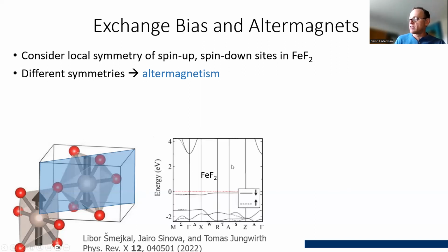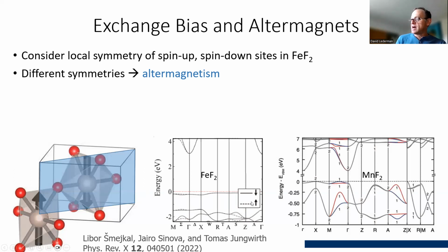And in fact, people have calculated the band structure. I think Sinova and others have calculated the band structure, taking this into account. And you can see that along certain directions in the crystal structure, right? This is like spin up and spin down, along this direction. You can see splitting, spin up and spin down. The red would be spin up and blue spin down. And here you have to look at the dotted lines. It's not in every direction.